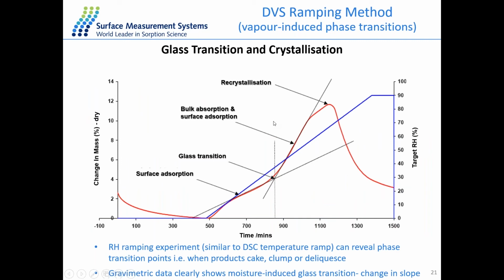And the other method we widely use is the ramping method, which is a quicker and much easier way to measure the stability of the solid material. So it's very similar to the DSC temperature ramp. In the case of the DVS technique, we will ramp the humidity from 0 to 90% RH at a constant rate. So that is the blue line here.